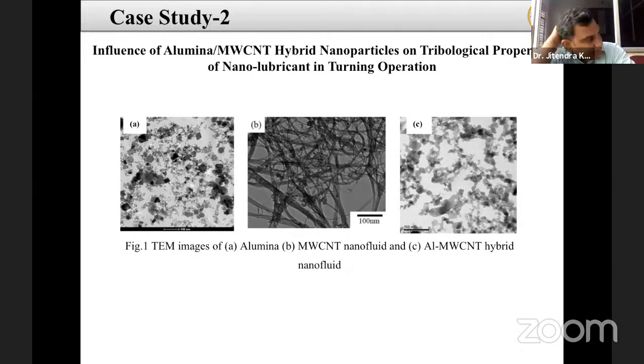So another case study, this paper published in the Friction journal, that is Springer. So here we just mixed the alumina and multi-wall carbon nanotube nanoparticle in the water-based lubricant, and then we performed the turning operation on aluminum alloy. And these are the TEM images of the mixed alumina and MWCNT nanoparticles, and you can see the alumina nanofluid, MWCNT nanofluid and alumina and MWCNT hybrid nano cutting fluid. So clearly we can observe the homogeneous mixing of alumina and MWCNT nanoparticles inside the fluid.